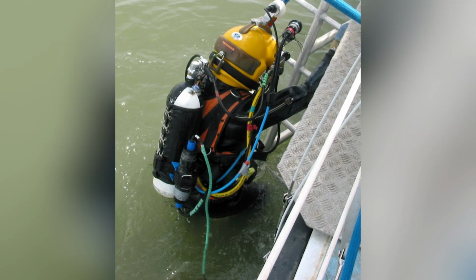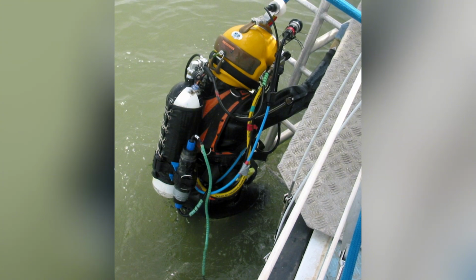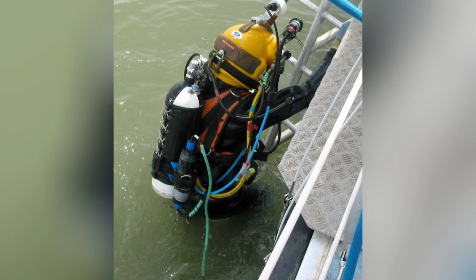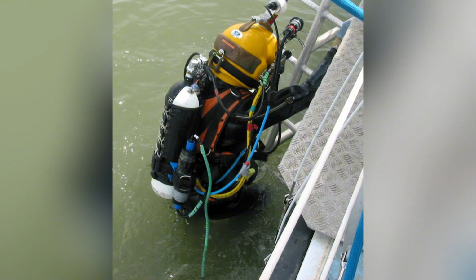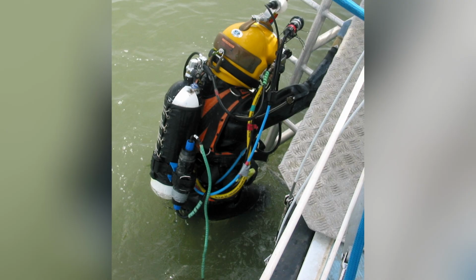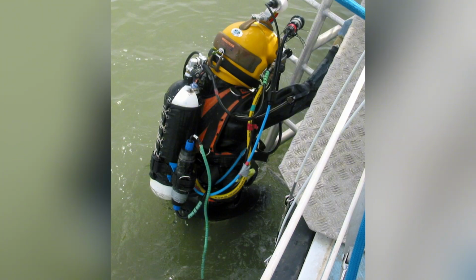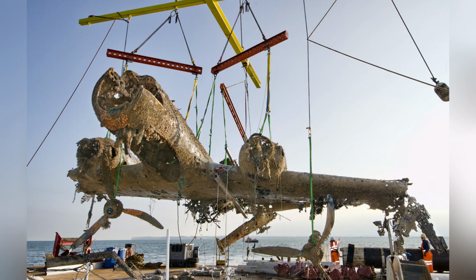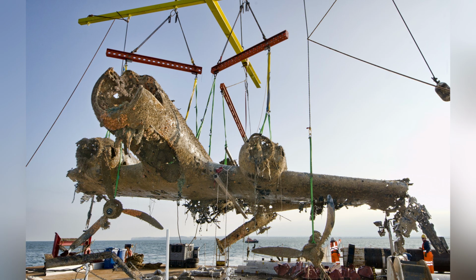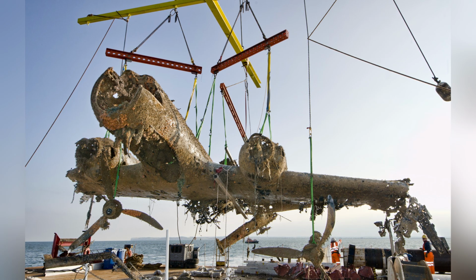They confirmed the presence of the twin Bramo 323 radial engines and the inverted orientation of the airframe. The tactile survey revealed that the aluminum skin was smooth to the touch in some areas, protected by marine growth, while other exposed sections showed the pitting of corrosion. The identification of the specific airframe as Werk Nummer 1160 transformed the site from a generic debris field into a singular historical asset.